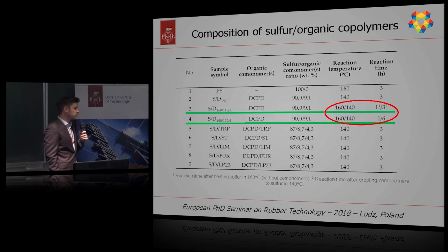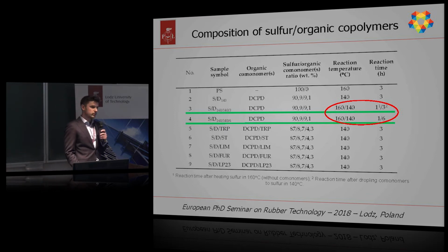During copolymerization, I tried to keep up similar conditions. So the reaction temperature was 140 Celsius degree, and the reaction time was 3 hours. But in case of sample 3 and 4, I used another approach, because I firstly heated sulfur to 160 Celsius degree to make sure that all the rings are open, and polymerize it for 1 hour. And then I decreased the temperature to 140, and I dropped the dicyclopentadiene and copolymerized it for 3 hours and for 6 hours.